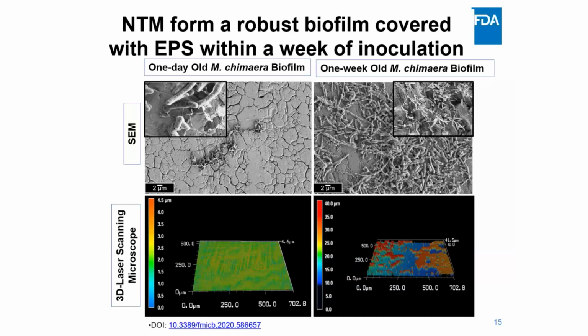So during the global M. chimaera outbreak, one of the major challenges was lack of high-resolution visual evidence showing how NTM biofilms actually form on medical device surfaces. So WEAC was one of the first laboratories to address this gap, capturing high-fidelity images of M. chimaera biofilms on clinically relevant materials such as stainless steel and titanium surfaces using scanning electron microscope and also 3D laser scanning microscope. So what you're seeing here is a time course comparison of biofilm development on stainless steel.